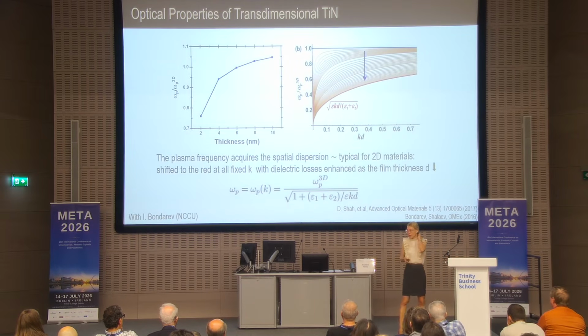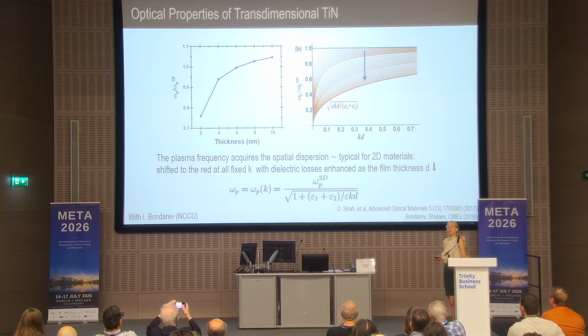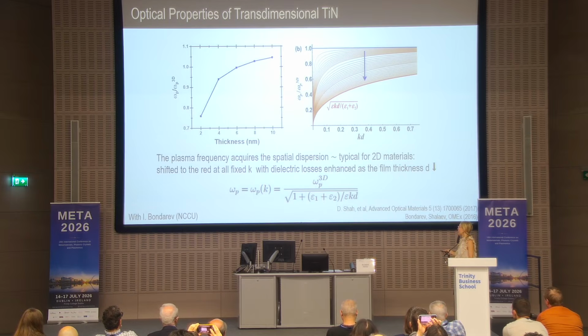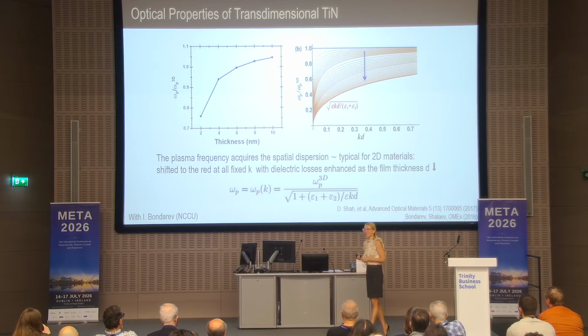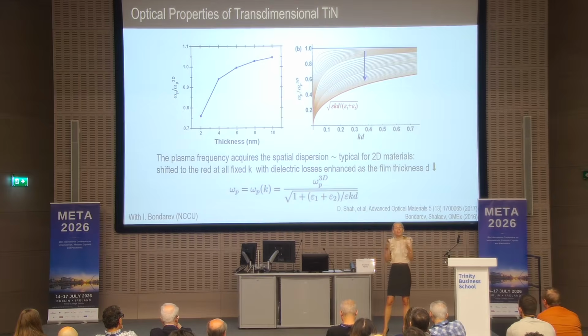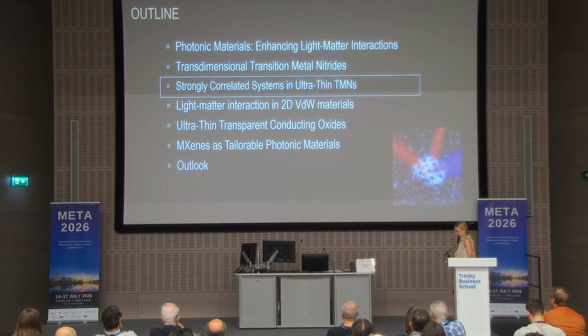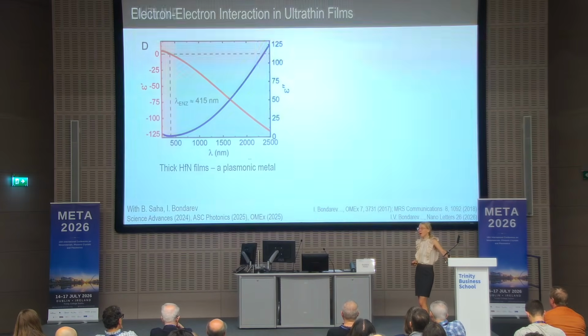Igor Bondarev here developed the quasi-classical theory to describe the properties of titanium nitride film in this ultra-thin regime, and showed that indeed the plasma frequency acquires a spatial dispersion, which is typical for 2D material. So it's a very interesting effect and very nice description, because you really show the transition from bulk, conventional thin films all the way to truly two-dimensional material. Okay, so what does it bring us? Well, it actually opens up a new realm for exploration, which goes far beyond photonics.